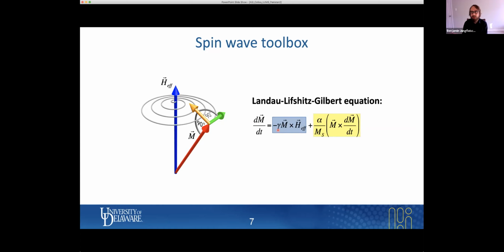Now, in a real material system, we have to face and account for damping, because if we do not have damping, then this precession would go on for infinite amounts of time. That's not physical. So it was Gilbert who introduced this phenomenological Gilbert torque term, with alpha the Gilbert damping parameter. It's a dimensionless quantity. It depends on the material. And Ms is the saturation magnetization. And the term here is m cross dm/dt, and this is represented by this orange arrow here. And as a result of this torque term, the magnetization is pushed back towards the equilibrium. As a result, the magnetization spirals around the axis defined by the effective magnetic field, and in equilibrium, it will point in the same direction. So we can use this equation to model our results. We can do this numerically, and I will show you this later on.